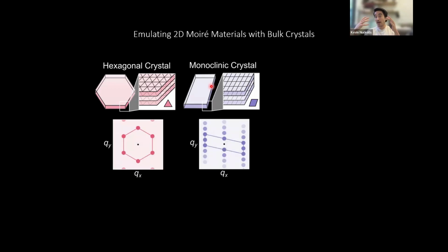So the idea is that I would place one of these single crystals in an X-ray beam and irradiate X-rays into that crystal, collect the Bragg scattering peaks, and analyze the symmetries of the X-ray pattern in order to understand the symmetries of the unit cell. So we can identify hexagonal crystals by their hexagonally symmetric Bragg scattering peaks. So these are 6-fold symmetric. And we'll identify monoclinic crystals because their diffraction pattern is 2-fold symmetric, where we can identify a monoclinic angle in that diffraction.